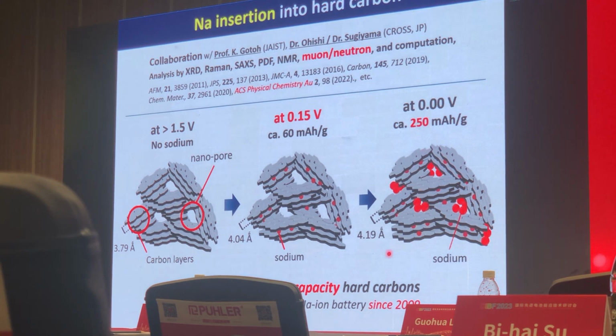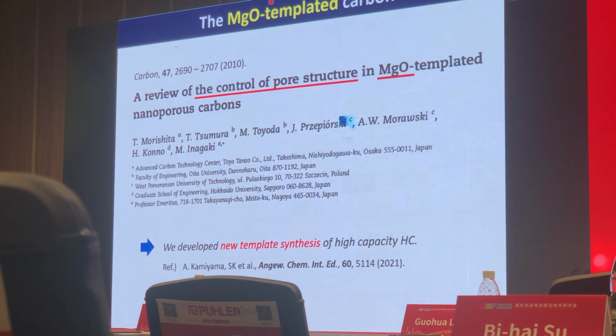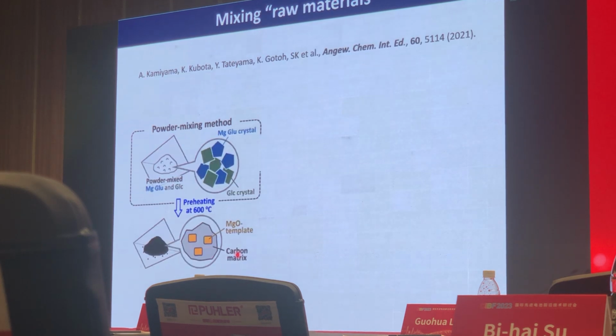Based on this understanding, we tried to prepare high-capacity hard carbon by using different starting materials and also different synthetic routes. And our latest success was magnesium oxide templated carbon. This synthetic route was developed based on the control of pore structure in magnesium oxide templated nanoporous carbon, which was published over 10 years ago. So based on these works, we successfully developed a new template synthesis of high-capacity hard carbon for sodium-ion battery.